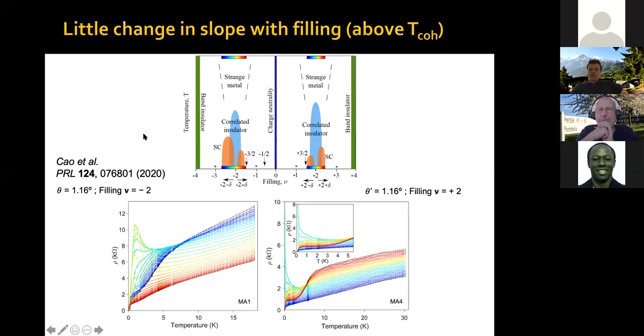We see nematicity in the superconducting state in all of the domes that we see. We always have anisotropies in the response of superconductivity to in-plane parallel magnetic field, in the critical current and in the critical field, okay? Now, you can look at our posted paper on nematicity, which we did in collaboration with Rafael Fernandes and Liang Fu. I'm an experimentalist and I like to go more by the data, but our collaborators have written there that it is extremely rare to have nematicity in the superconducting state, this type of very strong anisotropic response, if you have a plain S-wave order parameter. It is very hard to get that.